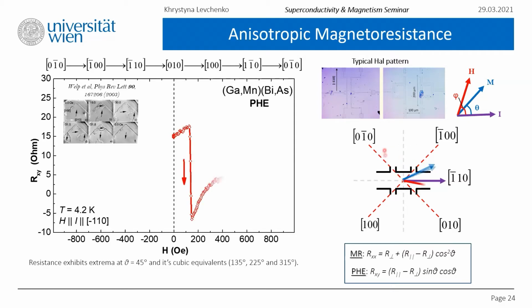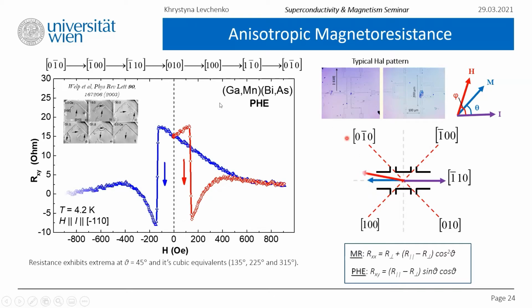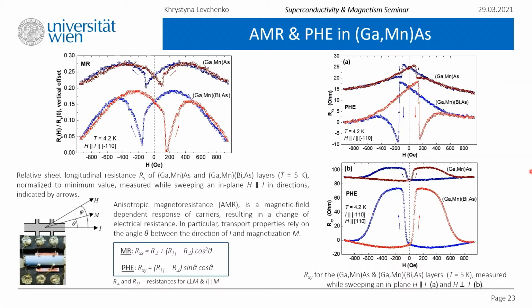So the rotation is between a set of easy in-plane cubic directions. This is a family of cubic planes, 1, 0, 0. We're starting with 0, -1, 0, and going a full circle. And this results in a four-fold transition between low and high values. So these extrema, 1, 2, 3, and 4, correspond to the angle theta equal to 45 and its cubic equivalents, 135, 225, and 315.